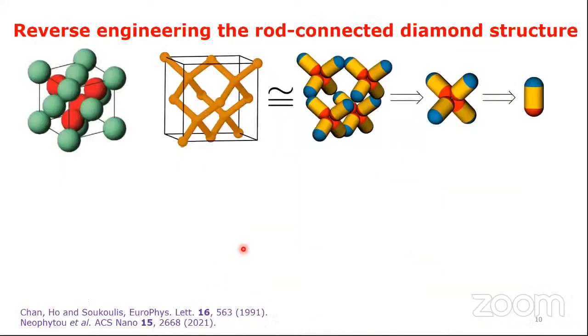I'm now going to extend this design approach to reverse engineer the so-called rod-connected diamond structure, which is known to be the champion photonic crystal because it supports the largest photonic band gap. Here, rods connect the nearest neighbor sites of the diamond lattice. A retrosynthetic approach on the colloidal scale, following the two-stage assembly scheme, takes us to tri-block patchy particles, but now with an elongated core. Because of the tetrahedral voids, we refer to this structure as segmented rod-connected diamond.